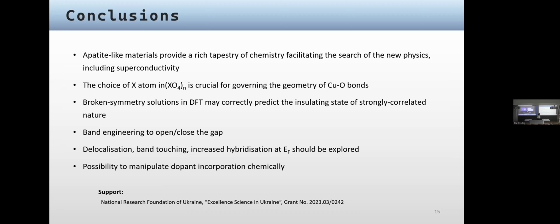No, something else. So from the summary of what is in the literature, the predicted electronic structure is rather flat. But the problem with particularly LK-99 is that it turned out to be insulating in the end due to strongly correlated effects. So here the idea is to change the composition, try to find another composition where this would not happen, and those flat bands will stay at the Fermi level. So in DFT calculations, it is a metal, but in reality, it is insulating. Yeah, basically yes.